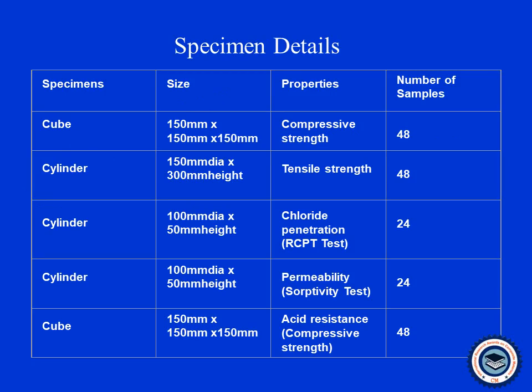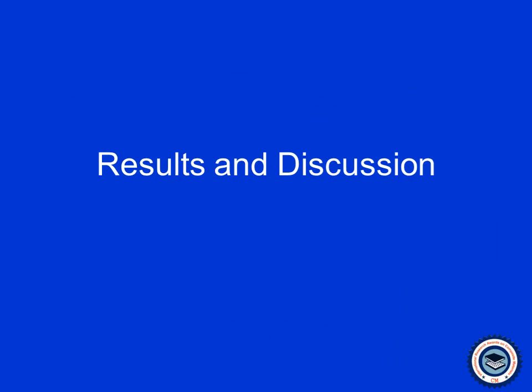We tried with cube specimens and cylinder specimens for conducting the experiments. The cube size is 150 mm by 150 mm by 150 mm, and the cylinder size is 150 mm diameter by 300 mm height. For doing the RCPT test and other tests, we used a cylinder of 100 mm diameter with a height of 50 mm, which is a slice cut from the 300 mm height cylinder. So 50 mm height we are maintaining for the RCPT test. Now we are going to see the results and discussion for the various tests.